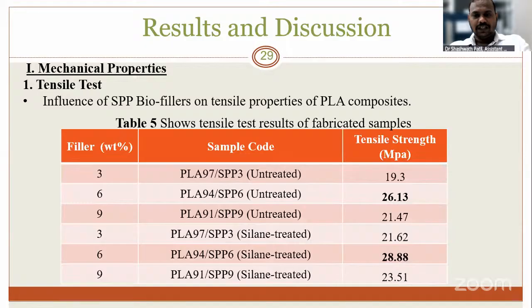Well, coming to the results part of the study, you can see the influence of these split pen powder biofillers on the tensile properties of the PLA composites. As you can see, in the 2 sets, for the untreated part, 6% filler is giving the maximum strength of 26.13, whereas for silane treated it has shown an improvement to 28.88. For the 3% filler, we attained the minimum of 19.3, whereas for the silane treated, 21.62. It shows that with silane treatment, the 6% filler is giving the maximum strength.